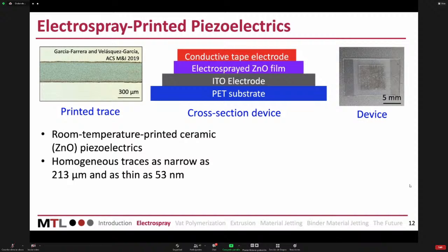For example, you can create this structure where you start with a flexible substrate like PET, that's a plastic. Then you can buy it already sputtered with ITO, or you can sputter it yourself. But then you electrospray your film. You can use these traces and weave them, so overlap them, so that you create an area. Then you close everything with conductive tape, or you can also spray these silver particles that we talked about. And here is your bulk acoustic resonator. With that, you can characterize it. There are all these instruments that can do it, and it's really neat.